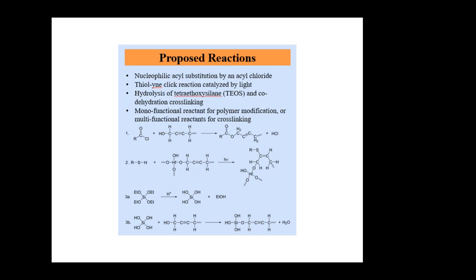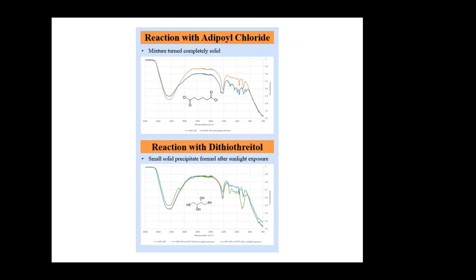We tried the acyl chloride substitution with adipoyl chloride, which you may recognize as a precursor for nylon. Upon adding the adipoyl chloride to the polymer, a solid precipitate immediately began to form, and the entire mixture turned solid within about a minute. In the FTIR, we see the presence of the acyl chloride structural features serving as bridges between polymer strands.